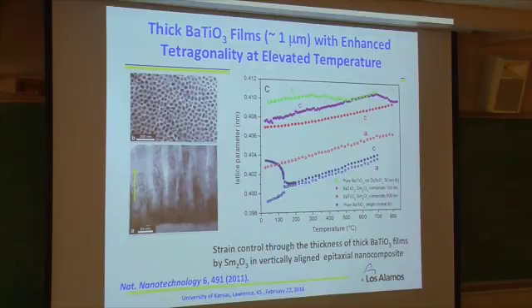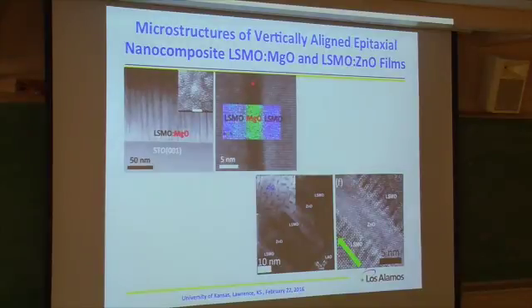Give you another example. Here, just to show you the cross-sectional TEM. For example, you can do this ferromagnetic LSMO material interface with MgO. We use MgO as a more like a control phase, or I call passive phase, and LSMO as active phase. You can use MgO to tune the magnetic property of the LSMO.